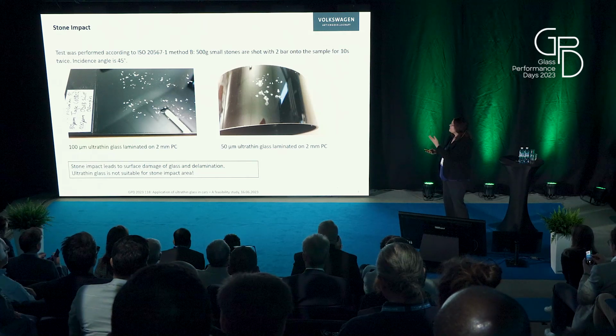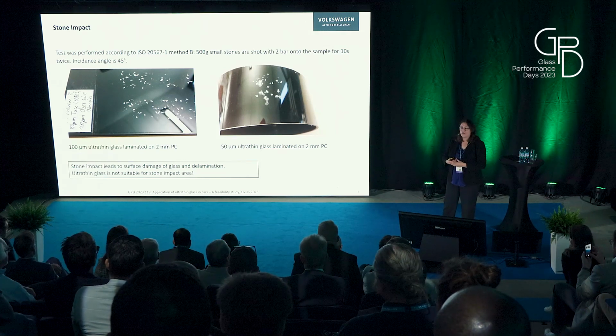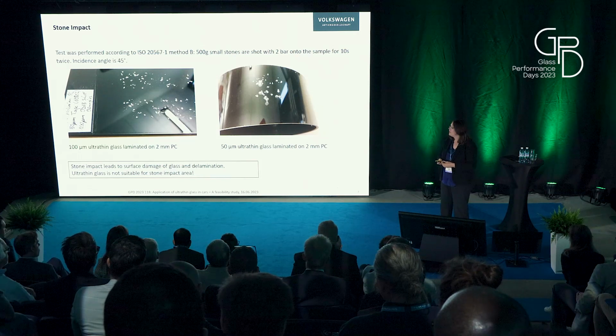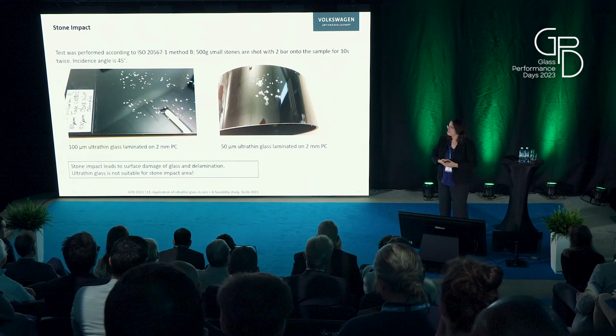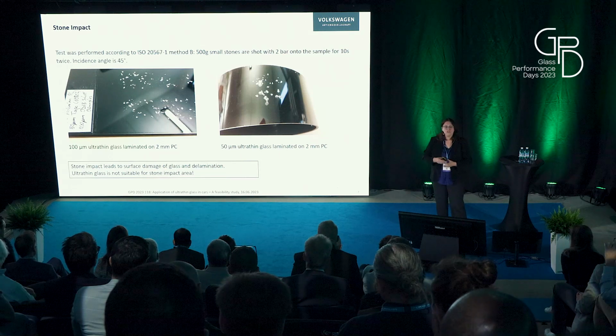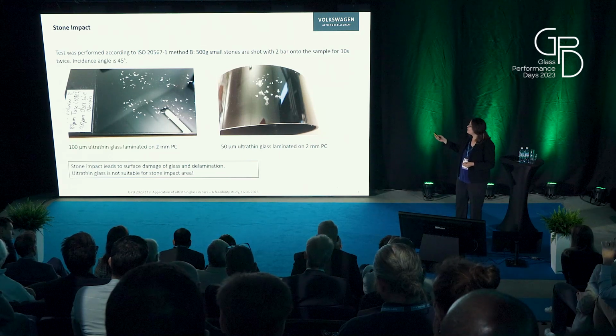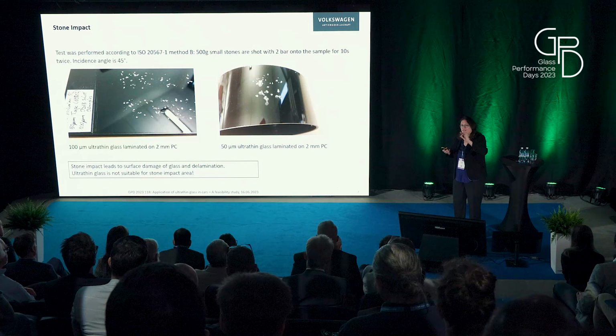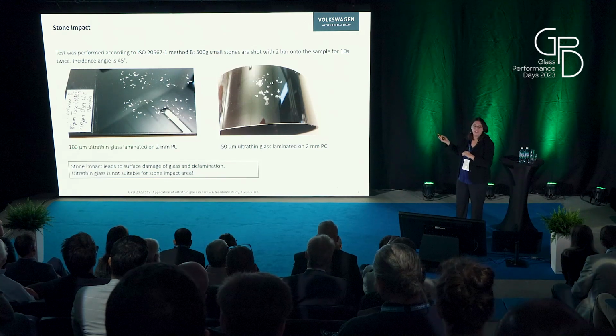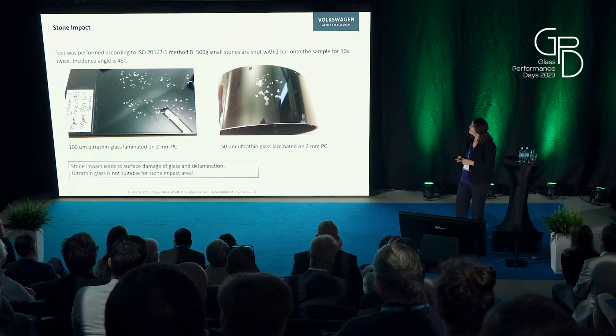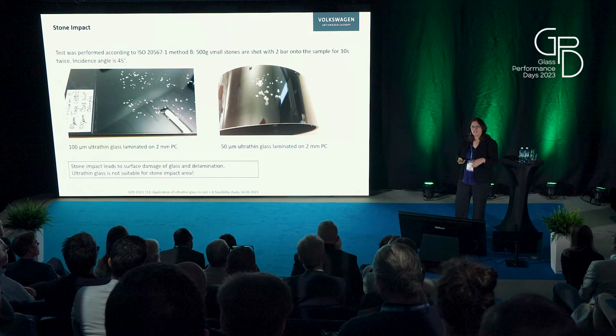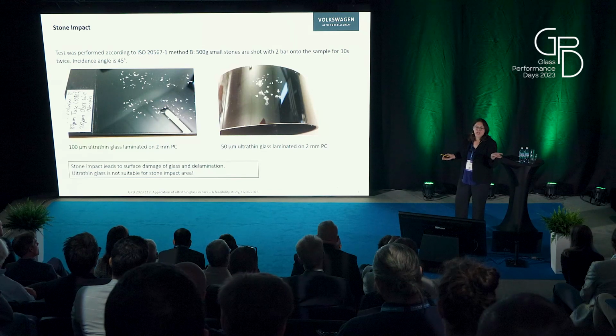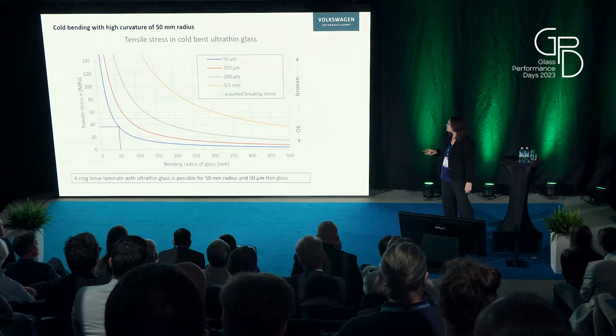Imagine if this would be a sensor cover with transparent polycarbonate behind. You wouldn't see too much through it anymore. The same for the ring lens. It's not only that the glass gets some impact, it's also delamination you see here. So it's not a good idea to use such laminates in stone impact areas, in the bumper and exterior. So we have to look for different locations.